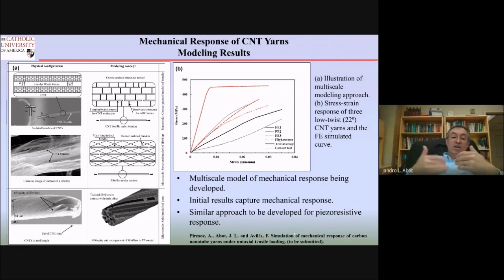So we basically tried to understand. It's a hierarchical model. The CNT fiber, you have to go to the nanoscale level. You have the nanotubes. Then the nanotubes agglomerate. They form bundles, and then the bundles form the yarn. So it's a hierarchical response, and we basically study each level, and we obtain the stress-strain response for the nanotube yarn at the end. And then we compare with different experimental results.